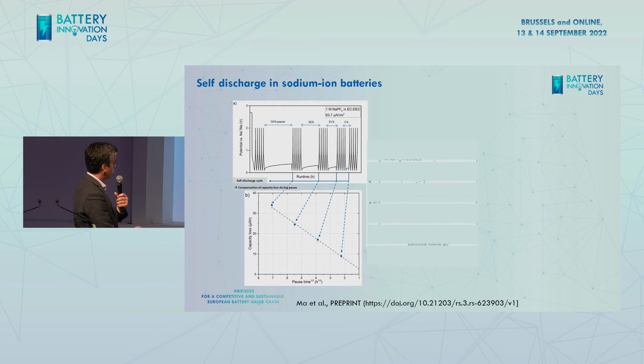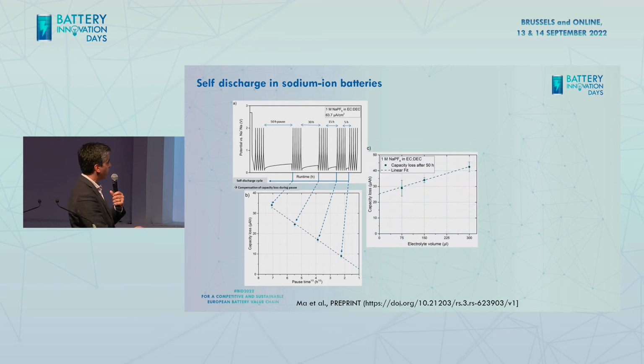So from this, we try to have a better understanding by continuing experiment, doing the same type of test, but changing the volume of the electrolyte. And you can see on the right that there is, again, linear relation between this capacity loss and the volume of the electrolyte. The higher the volume of the electrolyte, the higher the capacity loss is. So this is also another indication that this is diffusion limited, and from this we concluded that actually SEI dissolution into the electrolyte is a problem for sodium-ion batteries.